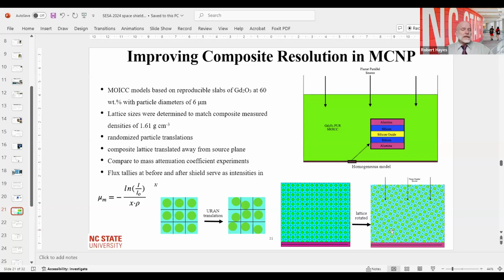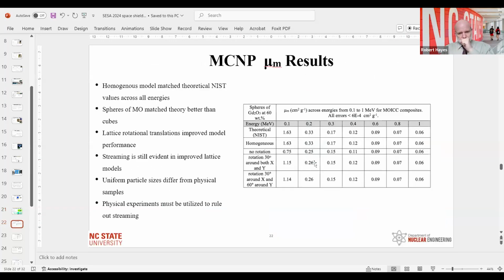Because when we did our validation, where I showed you earlier, where we validated the radiation transport with the calculated values, what was done is that we assumed that the stuff was homogeneous. So we actually didn't have the particulate in there. We just homogenized the thing, which is what you would get with an amorphous material, a better approximation. And there was no difference there between calculated values and measured values. And what we found here, I'm about to show you, is that we did see a difference between calculated and measured values if you use this approach. And that's given here in this table.